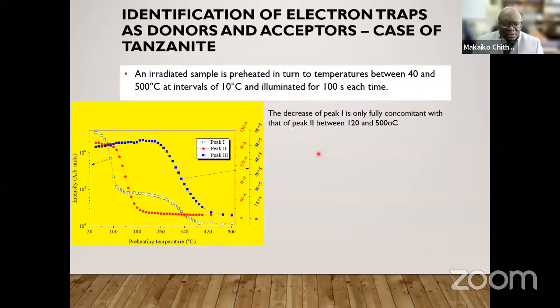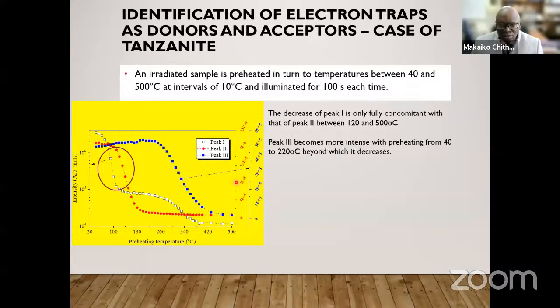The decrease of peak 1 and the decrease of peak 2 between 120 and 500 degrees seem to be concomitant. And in this area here where I've circled, you can see that as peak 2 decreases in intensity, as if it's removed by preheating, the intensity of peak 1 also drops. Peak 3, the higher temperature peak, becomes more intense with preheating and then decreases.